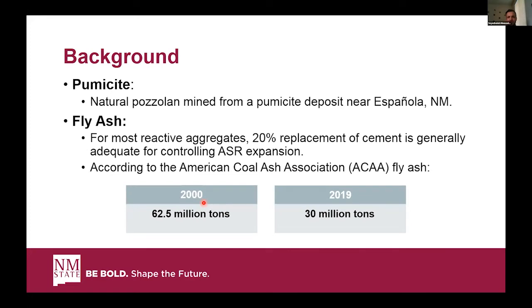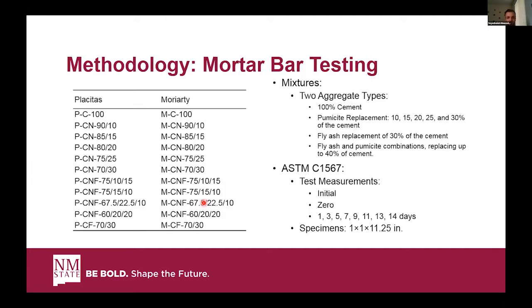We have used pumicite, this natural pozzolan made from a pumicite deposit near Española, New Mexico. And we have used fly ash as well, because we all know that at least 20% fly ash is needed to be added to the concrete in order to mitigate the ASR expansion. But as the American Coal Ash Association reported, the production of the fly ash is reducing. Like in 2000, 62.5 million tons of fly ash was produced, but just 19 years later, in 2019, just half of it, like 30 million tons of fly ash, was produced.